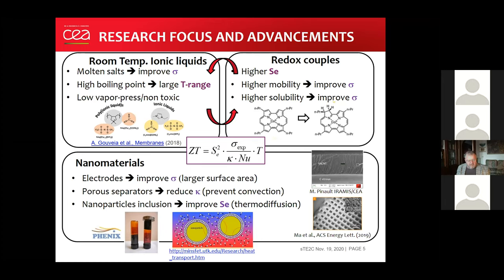Next, very closely related to the use of ionic liquids is the development of new redox couples. By changing the redox couples in transition metal ions, you can change the complexation of the ionic atmosphere around it, which can lead to a higher Seebeck coefficient.